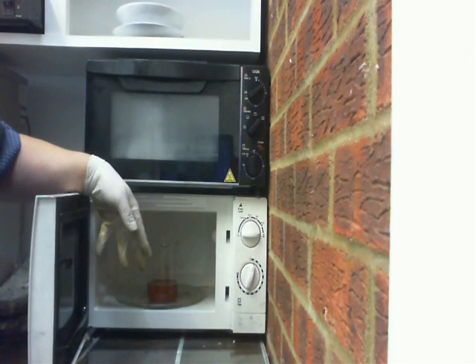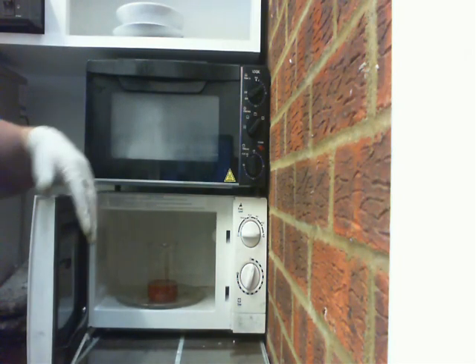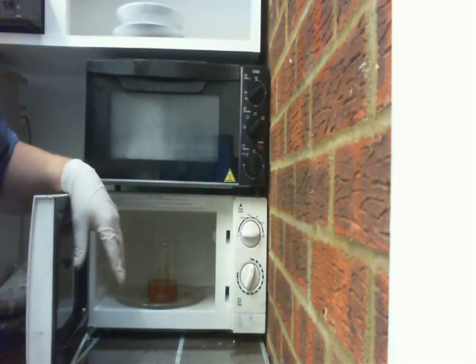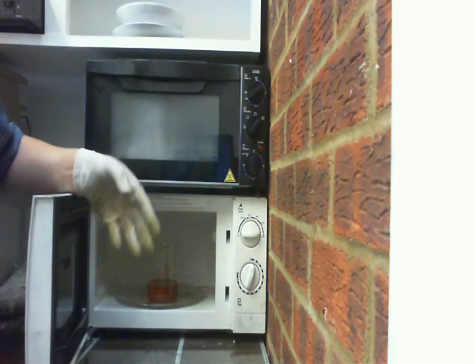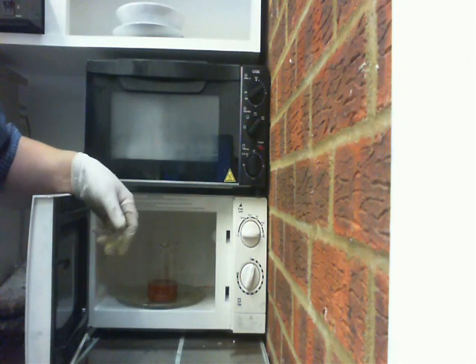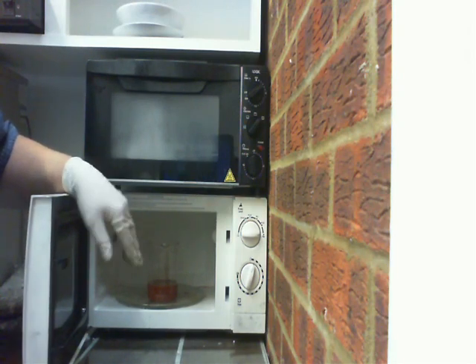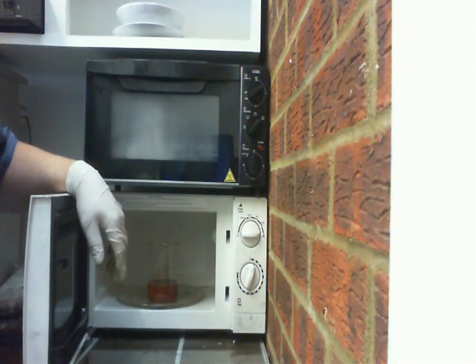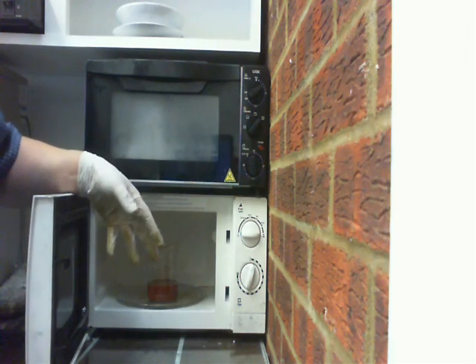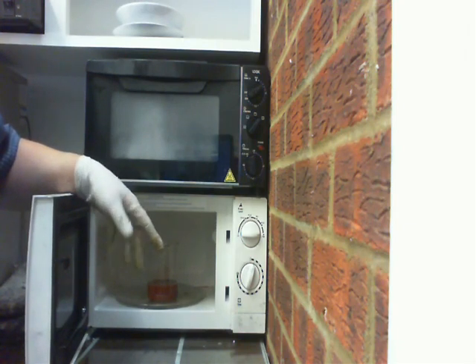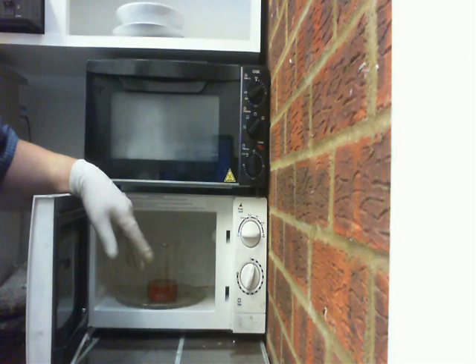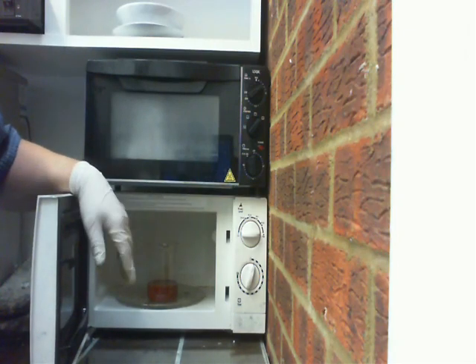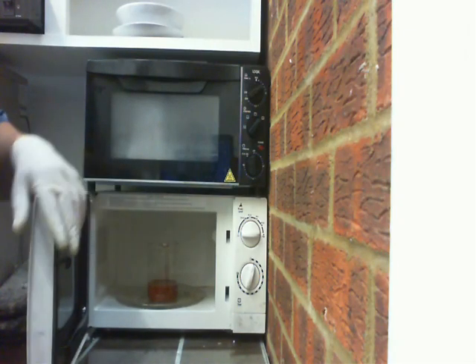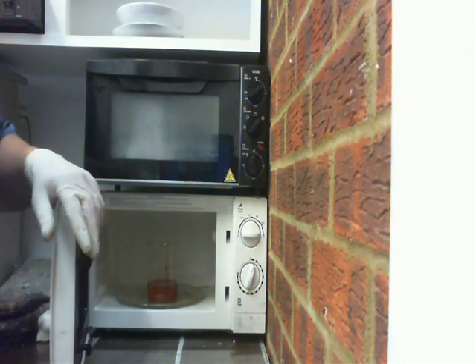If you're uncomfortable with using formic acid, you can use ascorbic acid. It just means that when you come to make an ink out of it, you've got ascorbic acid still left in there, and that can be a little difficult to get rid of. Whereas this goes all to copper formate, and the copper formate will just dissociate under photonic sintering or heat back into copper and releasing just a bit of carbon dioxide and water. That's why I use formic acid. Anyway, we give it another 5 minutes, and that should go from its brownish pink to its bright pink.